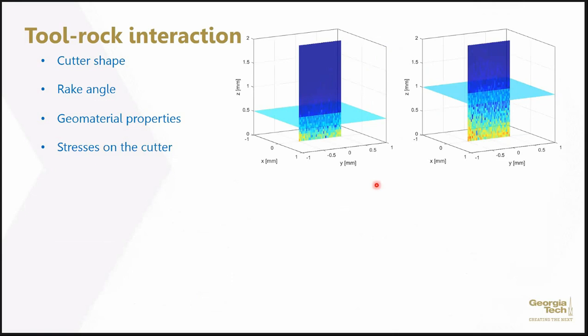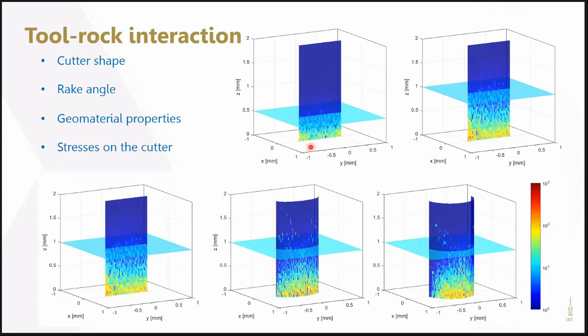So if we look at the stress distribution on these cutters, for the plate type of cutter, we can see lots of stress concentration at the bottom, especially at the edges. That's where the cutter will be damaged, or the cutter will deteriorate as the cutting progresses. However, if we have a curved surface, most of the stress concentration will be at the very front of the curved structure. So that will help to protect the integrity of the cutter, because the edges, which are easily broken or have higher stress concentration as in the plate, won't be a concern for a cutter with a curved surface.